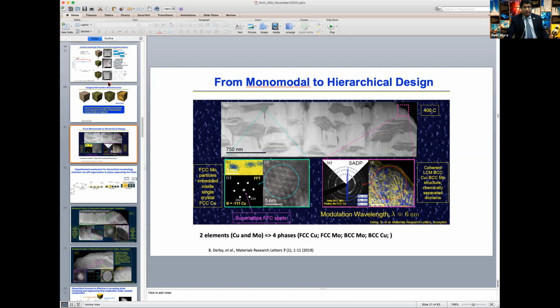Yeah, it depends if you can get a majority phase. I think what's happening in the island is that they're copper rich, and whatever moly is trapped is a minority phase. I'm guessing the minority might be 10% or so, and so it cannot form the stripe pattern, so it's forming these dots. So if you can find that kind of composition, then it should be possible in any spinodal. Okay, so it occurs at a very asymmetric composition. Yeah, exactly.